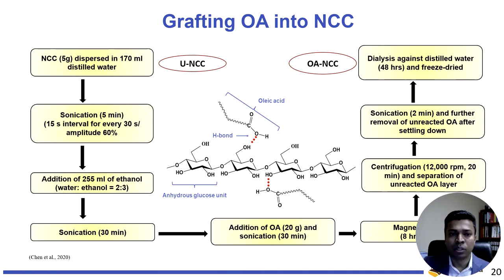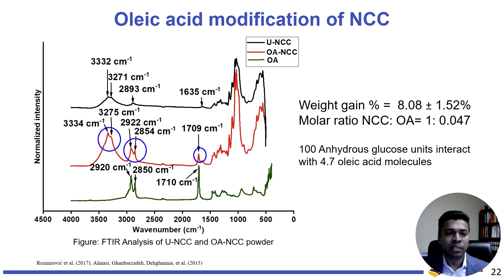I'm not going to go into detail about how we do the grafting, but just like in the previous research, we did look at how much oleic acid we grafted onto the nanocellulose surface. Based on the weight gain, we actually grafted around 8% oleic acid onto the nanocellulose. So if you take 100 grams of modified nanocellulose, you have around 8% oleic acid grafted onto the nanocellulose surface. And we did confirm this grafting using FTIR as well, just to make sure they actually grafted onto the nanocellulose surface.